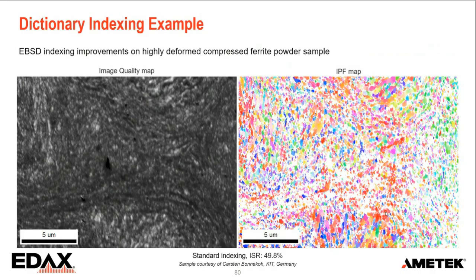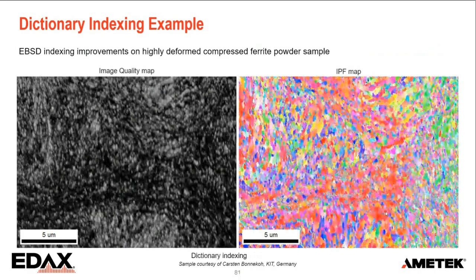So when we apply dictionary indexing to that, we get this. On the left, image quality. Well, image quality is based on the Hough transform, so we can't use that for dictionary indexing. So this is like a correlation index where we can see how good things are. And already we have less dark areas than before. And if you look at the IPF map here, there's clearly less noise in the image.